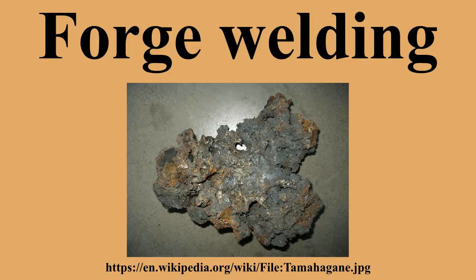Pure iron can be welded when nearly white-hot between 2500 degrees Fahrenheit and 2700 degrees Fahrenheit. Steel with a carbon content of 1.2% can be welded when orangish-yellow between 1700 degrees Fahrenheit and 2000 degrees Fahrenheit. Common steel between 0.2 and 0.8% carbon is typically welded at a bright yellow heat. A primary requirement for forge welding is that both weld surfaces need to be heated to the same temperature and welded before they cool too much.